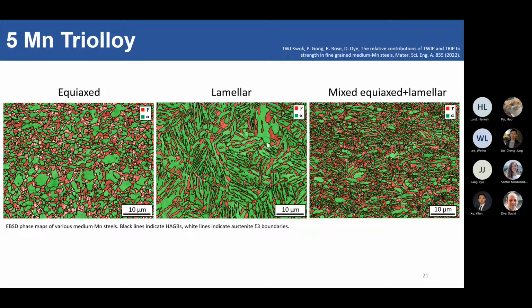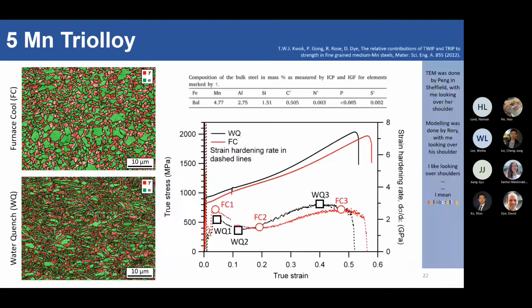So the question at the time was, which microstructure was the best in terms of tensile properties, toughness, and stuff like that? So these three microstructures can't possibly deform in the same way, right? One of them has to be better than the other. So that was the subject of our next study. So we took the equiax and the mixed equiax lamellar microstructure. I'm going to call it the furnace cool, the FC sample, because that's how you make it. So the FC sample and the water quench or the WQ sample.